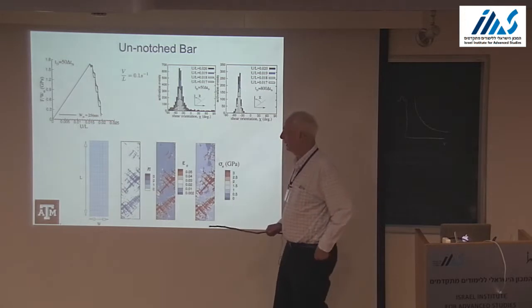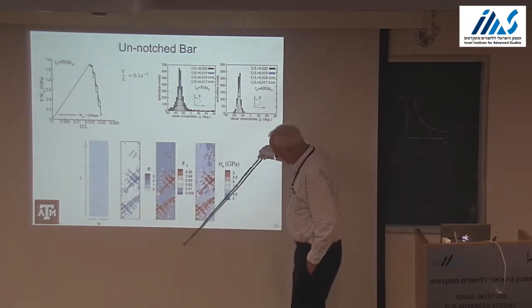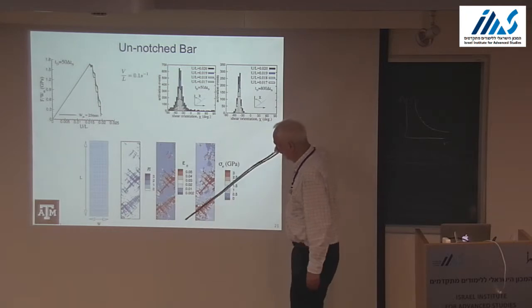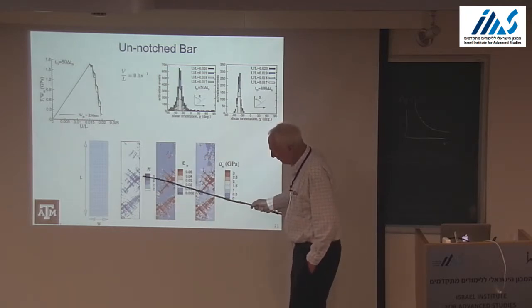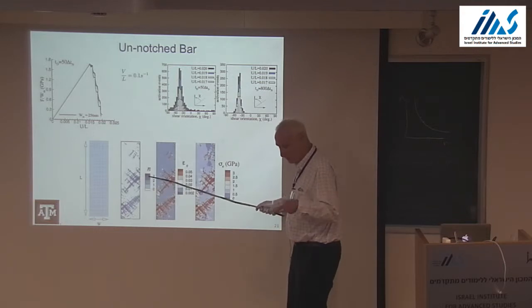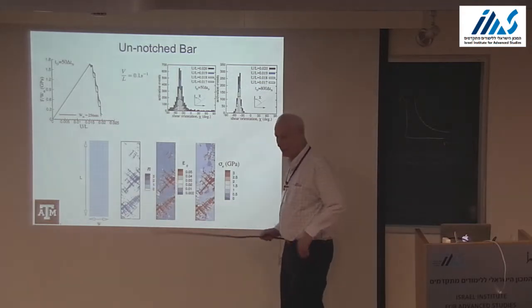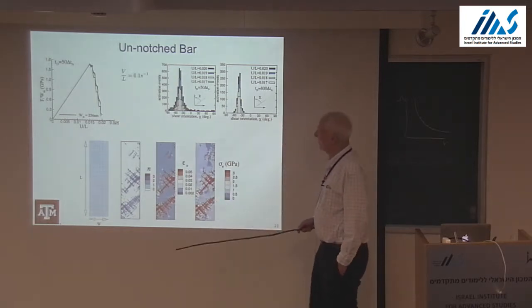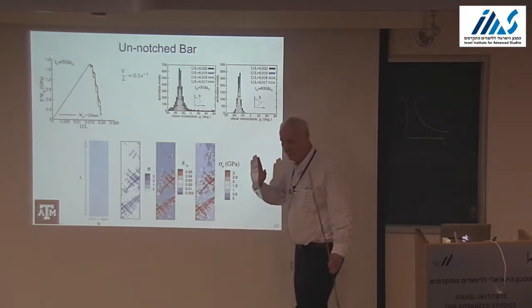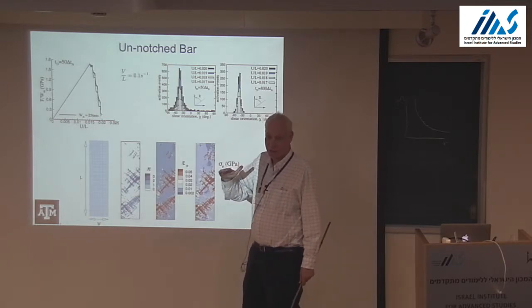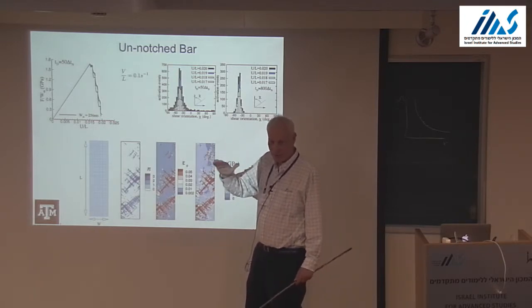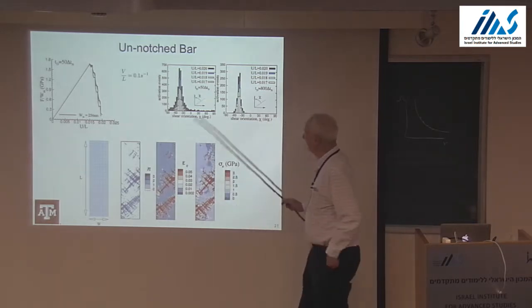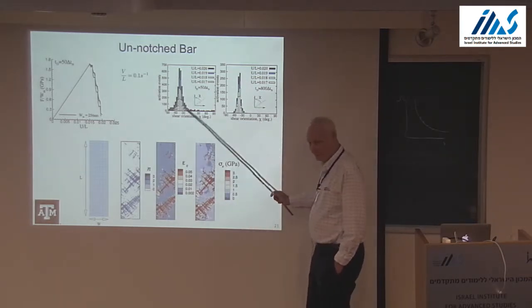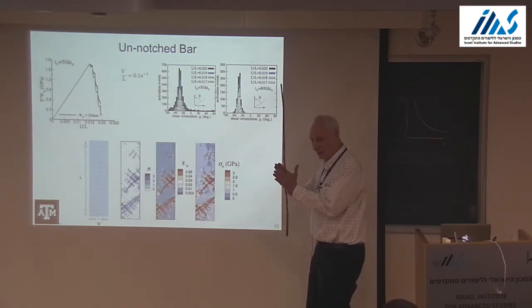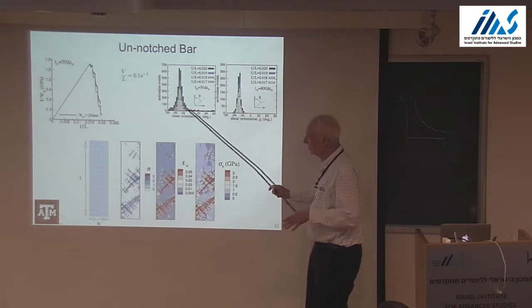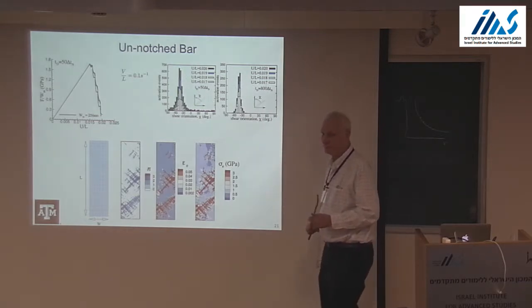So you see you get shear bands that form. There's stress, strain. This shows how many times something activates. So you can get here up to about 4 activations in a shear band, which gives larger drops. Here we pick the angle to be the angle of the maximum shear stress. So whatever the maximum shear stress is, that's the angle. The angle depends on this delay time. If there's a long delay time, the angles are sharper. If there's a short delay time, it's spread out.